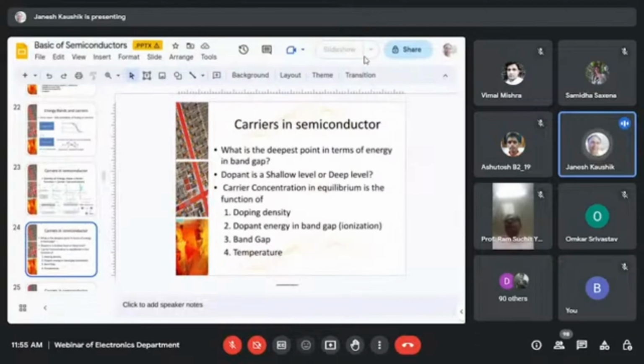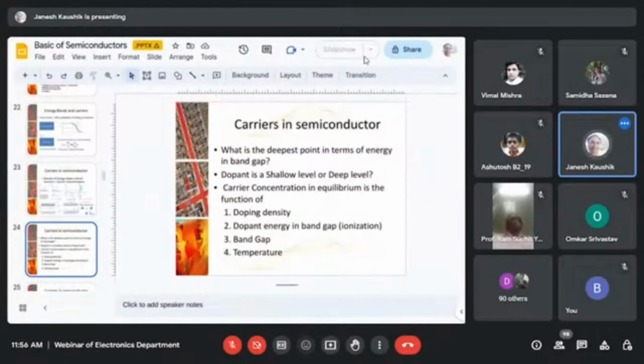So if you calculate the band gap of silicon, mid band gap of 1.12 is around 0.55 electron volt, and if you convert that to temperature it is huge, meaning thermally you can't excite a carrier from mid band gap to the conduction band, so you have to choose some other method. That's why we call it deep. It's a very deep energy level in the band gap. So carrier concentration in equilibrium is a function of doping density, dopant energy in the band gap where it is, whether it's partially ionized or fully ionized, and what the band gap is and what temperature you are working at.